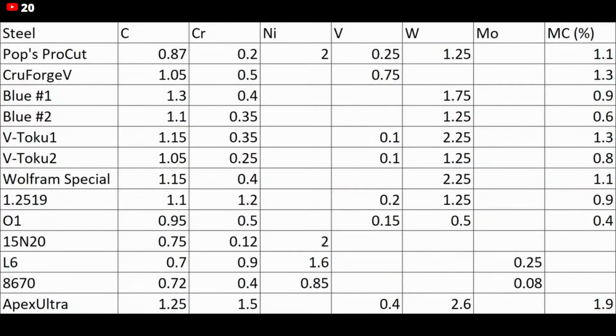To give some comparisons with steels that are in a similar class to ProCut, we could start by looking at the other high nickel steels, 15N20, L6 and 8670. They have a little bit less carbon because they don't have the carbide formers, tungsten and vanadium. And the Blue Steel series of steels or V-Toku or Wolfram Special, those all have some fraction of MC carbide.